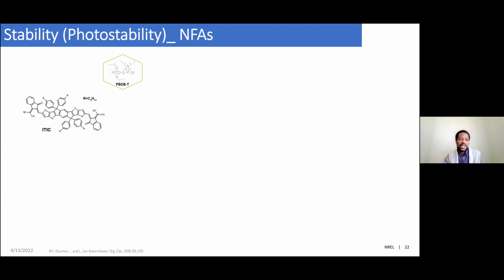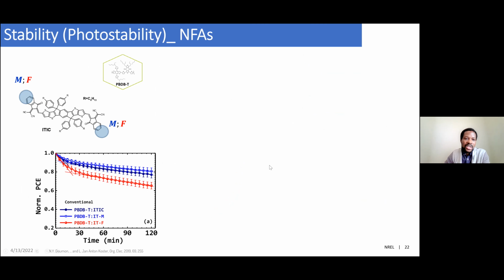So what we did next is to look at the ITIC and its derivative. And what the chemist community also did is to play with the outer benzene ring by substituting them with CH3 and fluorine atoms. And clearly here we can see that in any case, fluorine is bad news for stability in terms of photo-induced degradation. And when you add a methyl group, that improves slightly the photostability. Of course, if you do these changes in terms of efficiency, you gain a lot.